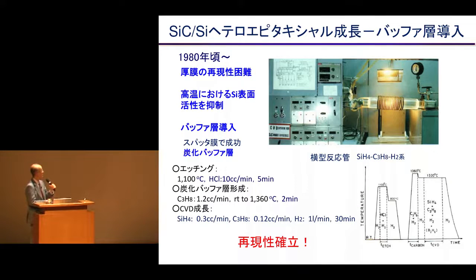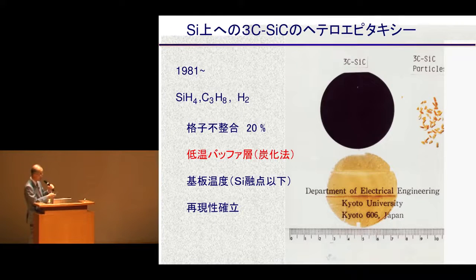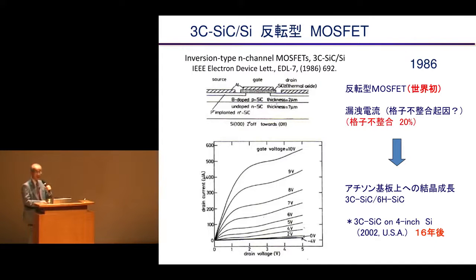So it took about a decade to come up with a certain achievement. I introduced a buffer layer for silicon carbide, which could be developed on a different material substrate. It was about 1980 that we succeeded, and we were able to use the handmade reactor to develop reproducibility on a silicon substrate. Silicon carbide was grown. So we succeeded in that.